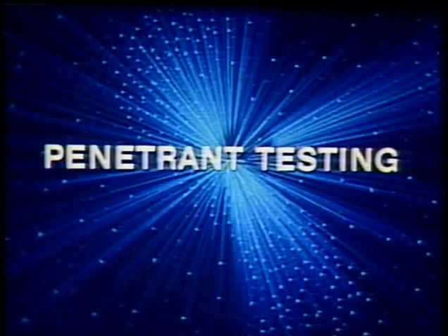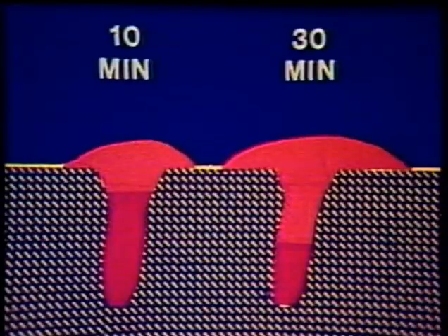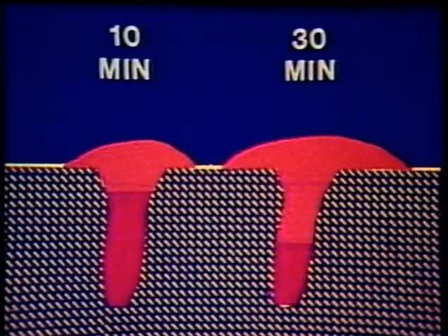Penetrant testing is an invaluable quality control technique. However, like visual testing, care must be taken in drawing conclusions. For example, the depth of a flaw cannot reasonably be measured. The inspector can only see penetrant indications that appear on the surface. In general, though, the larger the flaw and the longer the time allowed for penetrant bleed-out, the larger the indications will appear. But because the amount of bleed-out is based on the volume of the opening and not the depth, accurate depth measurements are not possible.